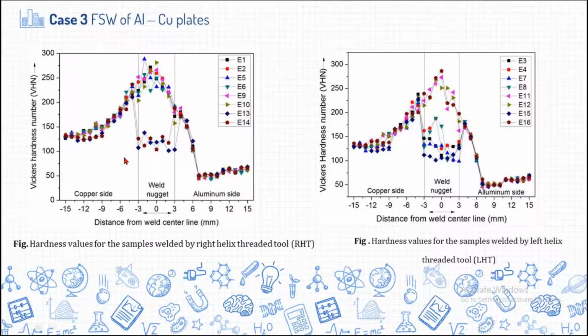And these are the hardness plots. If you observe at the center of the weld line, there is more hardness compared to base material. The base material hardness is around 125, but here at the center of the weld, more hardness was observed. But for a few experiments, E1 is experiment 1, experiment 2, for experiment number 14 and 13, showing some poor hardness at the center of the weld nugget zone for right hand thread tool.